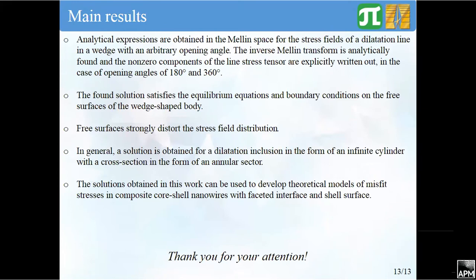And finally, in conclusion, analytical expressions are obtained in the Mellin space for the stress fields of a dilatation line in a wedge with an arbitrary opening angle. The inverse Mellin transform is analytically found, and the non-zero components of the line stress tensor are explicitly written out in the case of opening angles of 180 degrees and 360 degrees.